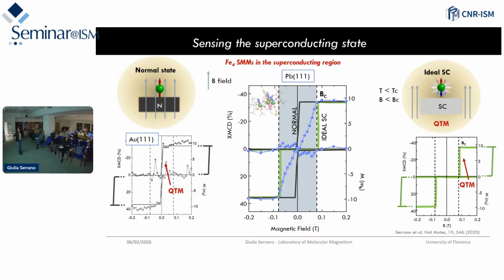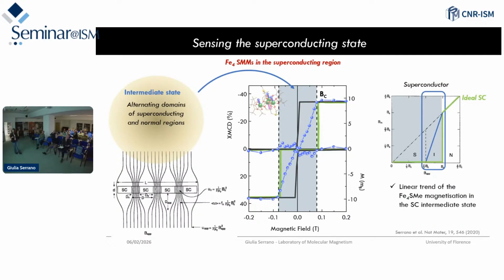Then what we observed some years ago is that at BC, the real data that we measure, the blue dots, the magnetization starts to decrease at BC, but it does it slowly with a linear trend. So we started to dig into the theory of superconductivity and actually rediscovered that superconductors are not ideal.